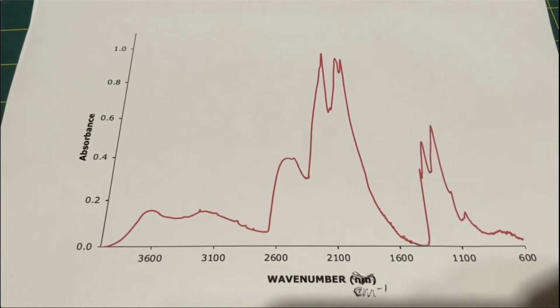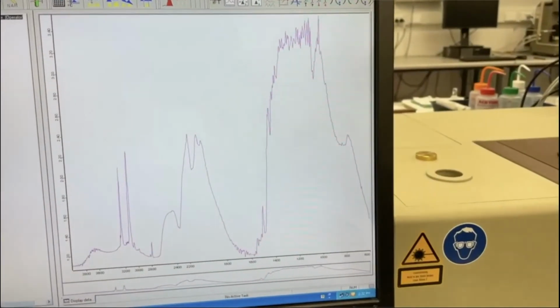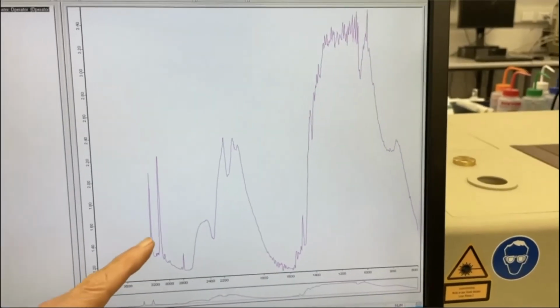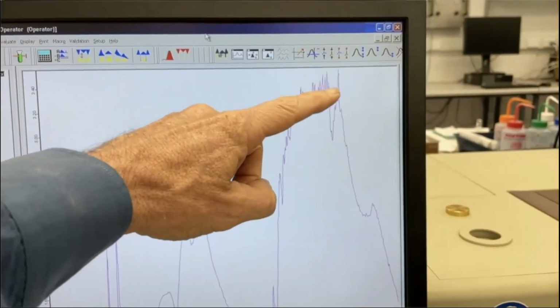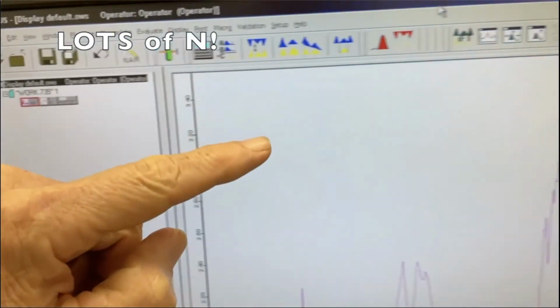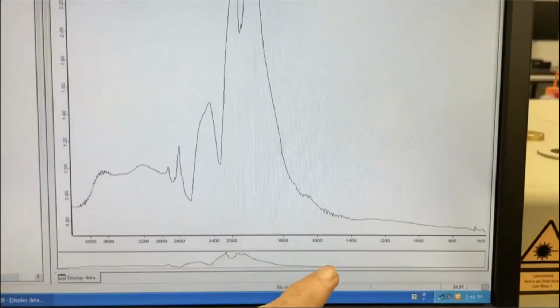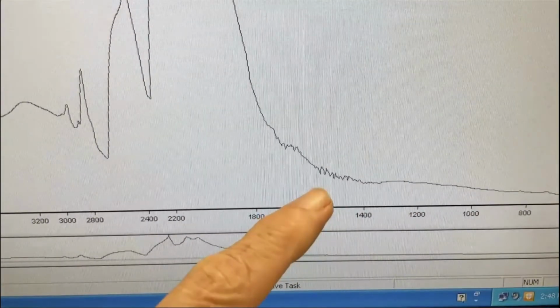So now let's go back to that blue diamond which I was looking at earlier. Here is its infrared spectrum. You notice a huge one phonon area and also some enormous peaks in the hydrogen area. But if we look back at the one phonon area, the saturation there, it's not really a saturation, it's the opposite of that, because the absorption is around 3.4, which is equivalent to about 0.04% transmission. At the other end of absorption, we have type 2 diamonds. These show very little absorption in the one phonon region.